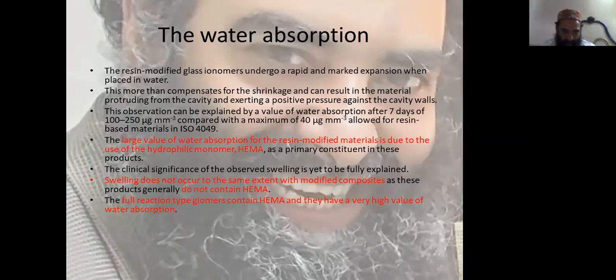The clinical significance of the observed swelling is yet to be fully explained. That is not clear. Swelling does not occur to the same extent with modified composites, as these products generally do not contain HEMA. The full reaction type giomers contain HEMA and they have a very high value of water absorption.